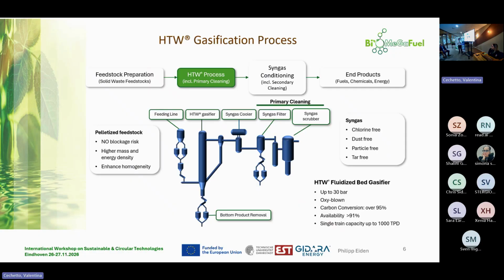This helps in improving the efficiency of the system. Typically, the gases which exit our cyclone are in the order of around 900 degrees, I would say, and it requires some cooling. So it passes through syngas cooling, where the temperature drops to around 350. And finally, we have a syngas filter where dust in the order of few microns are filtered with an efficiency of close to 99.9%. These are ceramic filters which we use.